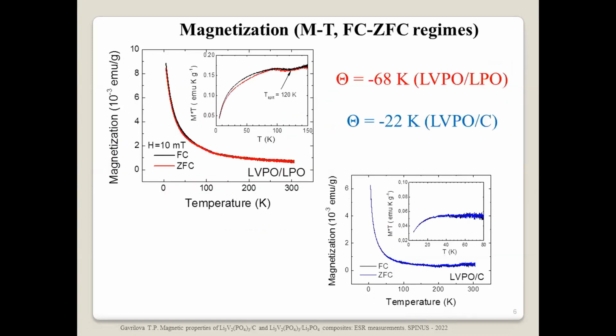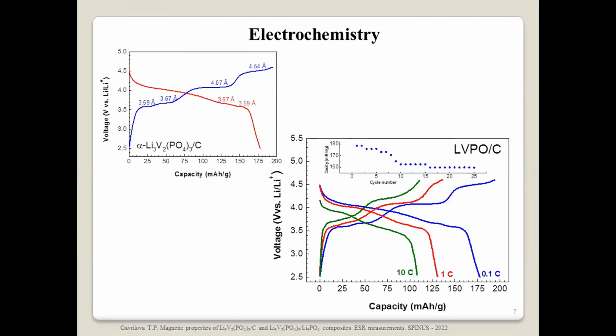To prove this suggestion, we performed additional measurements of magnetization in two different regimes, field cooling and zero field cooling regimes. And we see the splitting here on the left. One can see the splitting between two types of curves only in one sample, only in the composite with lithium phosphate, which, as I have already told, has the higher value of the Weiss constant. And we suggest that this magnetic inhomogeneity can influence the electrochemical properties. For example, the electrochemical measurements were performed for the composite with carbon, and it has a rather high value of electrical capacity.